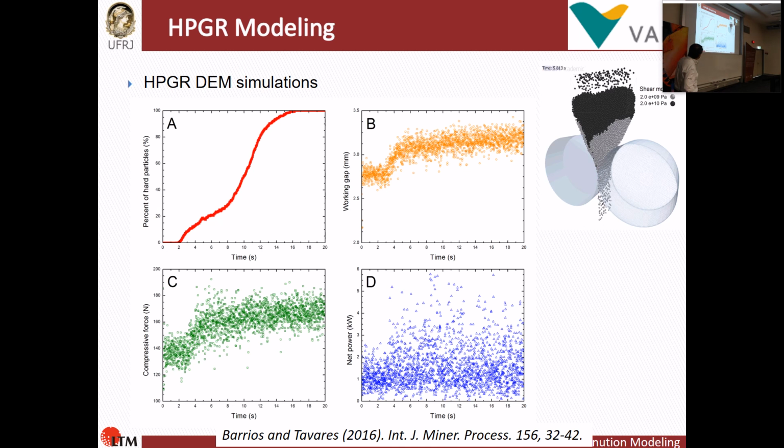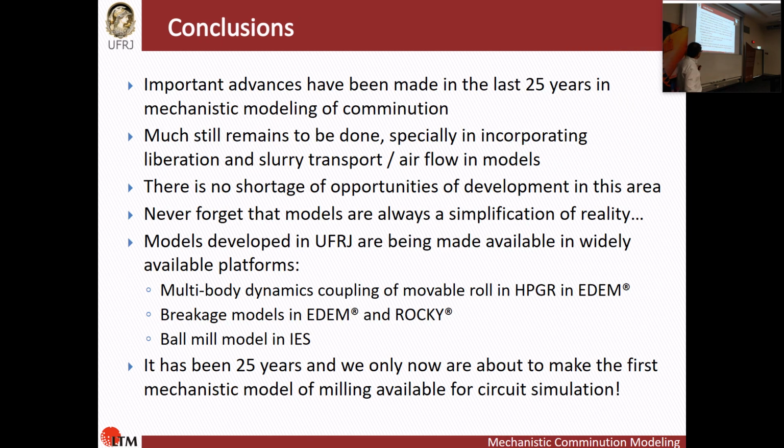But then you look at how the gap responds. The gap changes level because it's dealing with a much harder, much stiffer material. And the forces, of course, go all over the place, but they still increase because it's dealing with a stiffer material, and the power is like, no comment at all. But really there's a lot that can be gathered from this, and we're doing a lot of work in this area to harness as much information as we can from a realistic simulation, to be able to apply it to solve real problems.